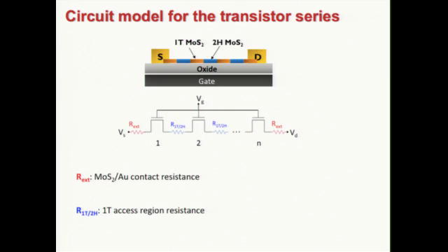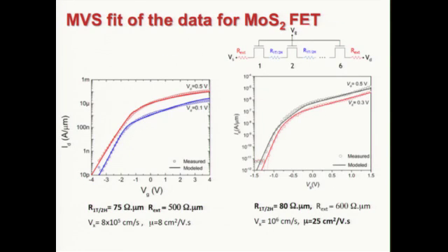We have n transistors in series with this internal resistance, which represents the metallic-semiconducting MoS2 junction resistance, and two external resistances, which represent the metal-MoS2 contact resistance. It's very important for us to know what this resistance is. So here is the fit. I have two examples. This is the tri-layer result that we already saw, and this is a monolayer CVD MoS2 device. As you see, the fit is relatively good.